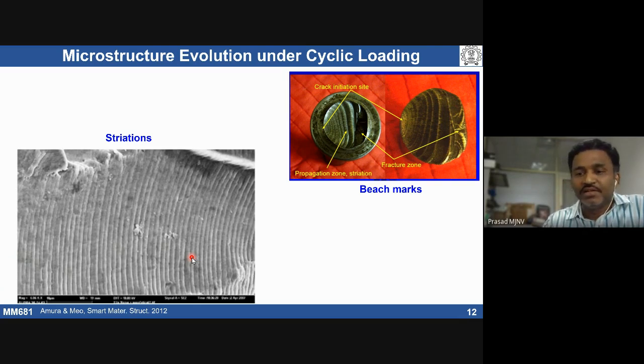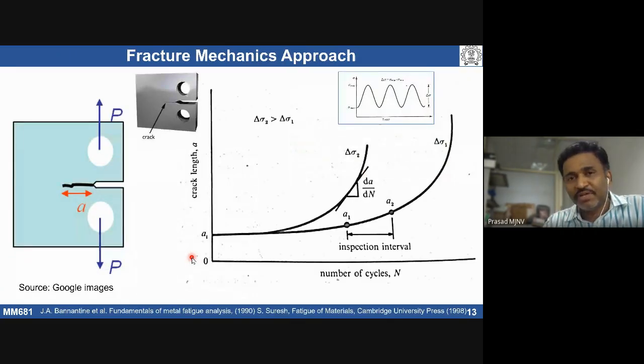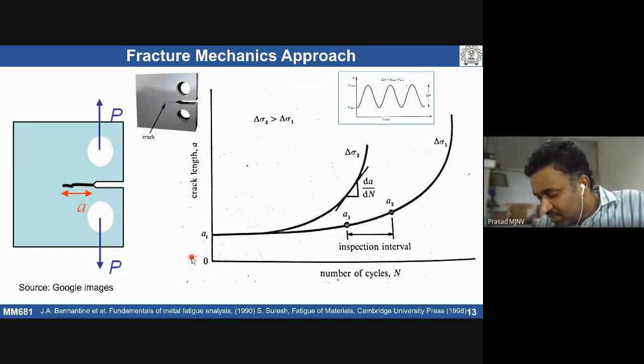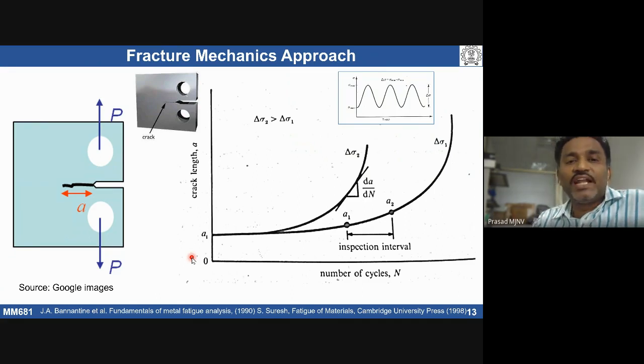Another important thing, because we always talk about it, is the fracture mechanics approach. One has to understand how the crack is propagating, how the crack is propagating with number of cycles. So what does the fracture mechanics approach involve? Take a compact specimen and monitor the initial small crack, how it is propagating with a given stress amplitude or stress range. Here, when I say stress range, it is sigma maximum minus sigma minimum, and the stress amplitude is that divided by 2.